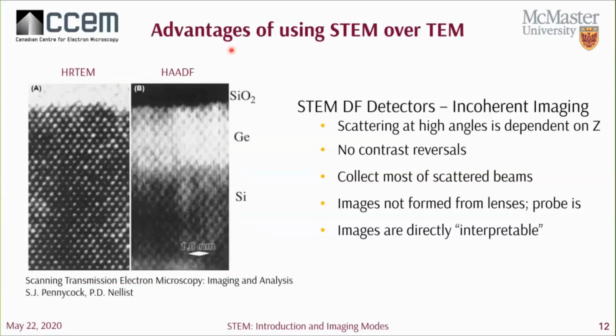Okay, so here we can see an example of Z contrast in comparison with the HRTEM image shown here. Here we can clearly see the germanium layer is higher in contrast, so the germanium is heavier than silicon and oxygen, and so it shows up brighter in contrast. Additionally, we can see the design of the detector is annular in shape, so we can collect most of the scattered signals, as opposed to dark field TEM imaging, where we need to isolate a fraction of the scattered beam to produce a dark field image. So we can collect most of the scattered electrons using these annular detectors.